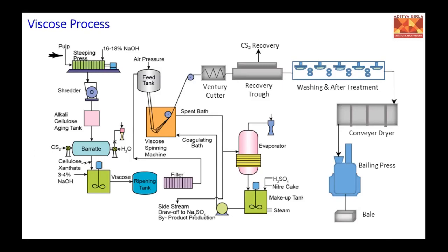It goes through the pulping process. There are different pulping processes like the kraft process and the sulfite process, and the pulp has very stringent parameters set for the viscose process. Therefore this is a specialty grade pulp, a high purity pulp, wherein the cellulose percentage is typically more than 90%. First it is reacted with caustic solution. We treat it with 18% caustic solution and form alkali cellulose. The hydroxyl groups on the cellulose chains react with NaOH to form ONa. We call it alkali cellulose or alkcell.